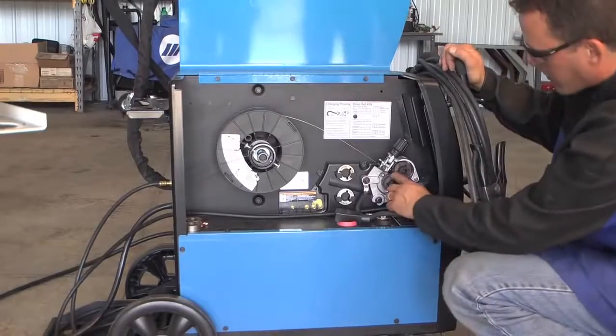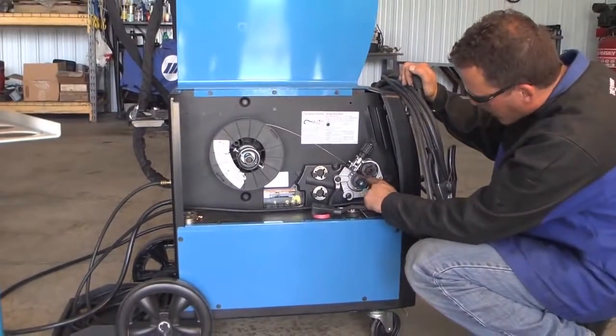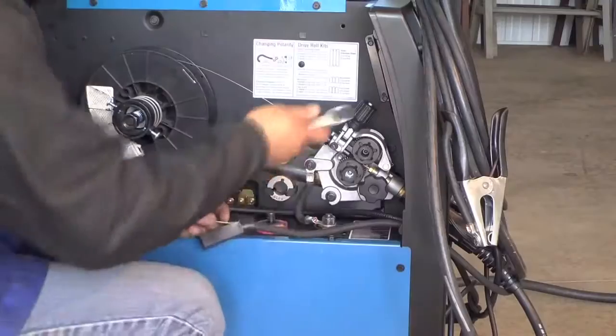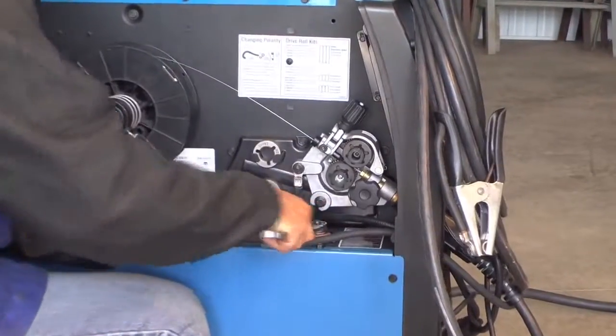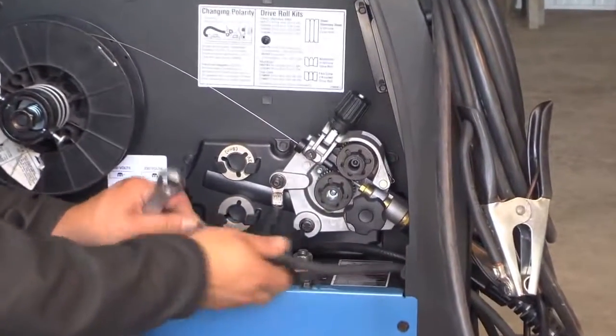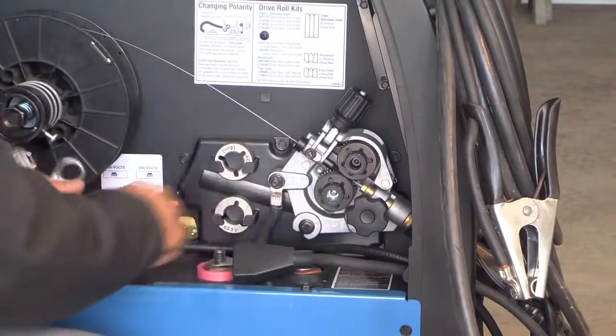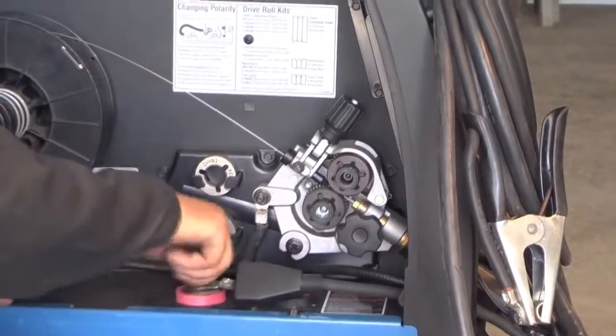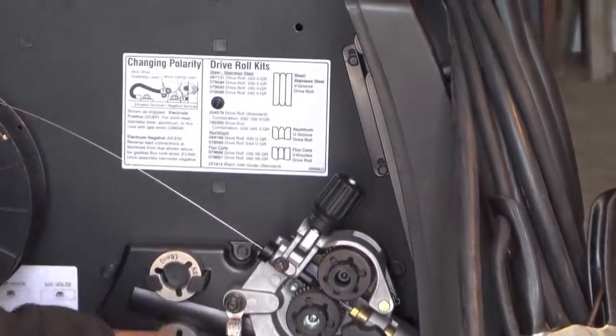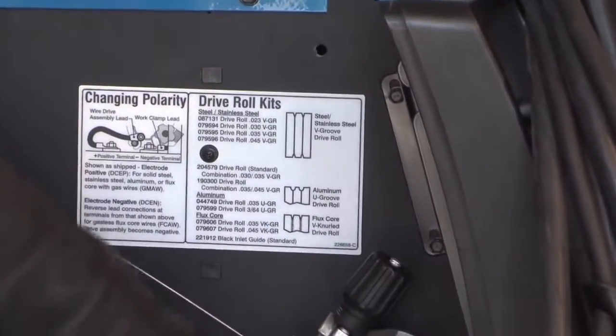For the drive rolls with flux core welding, you're going to want to use the knurled groove drive rolls. Otherwise, it will not feed the wire properly if you use the smooth drive rolls. And also for flux core welding, you're going to want to change your polarity to electrode negative. That's electrode positive for MIG welding, but for self-shielded flux core, you need electrode negative.